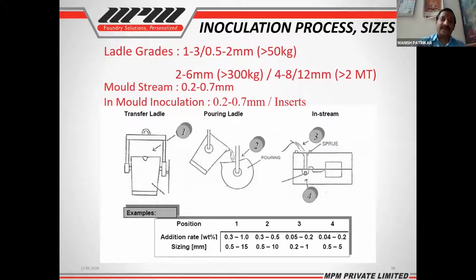So for the greater than 50 kg ladle and lesser than 300 kg ladle, we can use 1 to 3 and 0.5 to 2 mm inoculants. For greater than 300 kg ladles, 2 to 6 mm, and for greater than 1 ton, 2 ton, 4 to 8, 8 to 12 mm, these sizes are recommended. Then for mold stream inoculation, 0.2 to 0.7 is advisable, and for in-mold inoculation there are inserts available for the bigger castings. But usually for the pouring, where pouring machines and auto pour systems are there, 0.2 to 0.7 mm is the normal recommended size.